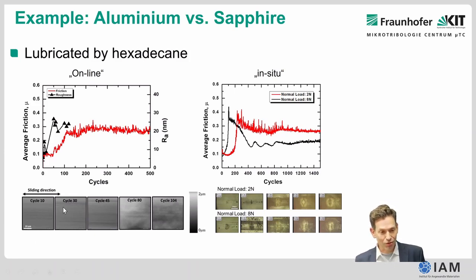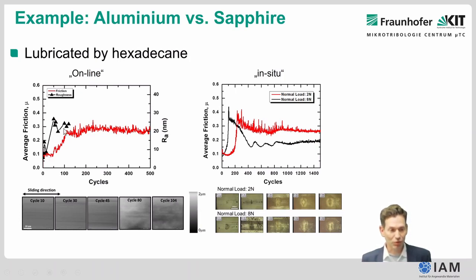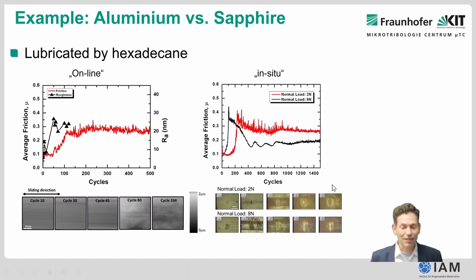We used a digital holographic microscope to look at the evolution of topography in the wear track, showing roughness in false colors — the color bar goes from 0 to 2 micrometers. In the beginning we see a roughness increase, which reflects the increase in friction to some extent. Looking into the contact we can also see transfer occurring from the aluminum surface to the sapphire sphere, which could be another mechanism responsible for the friction increase.